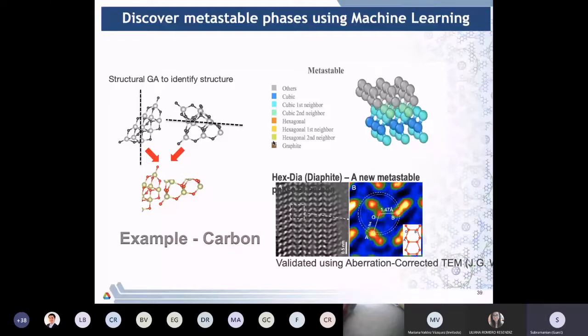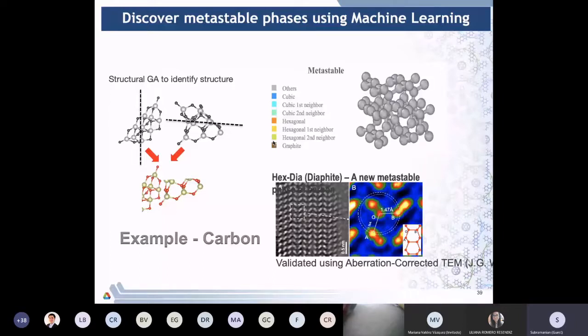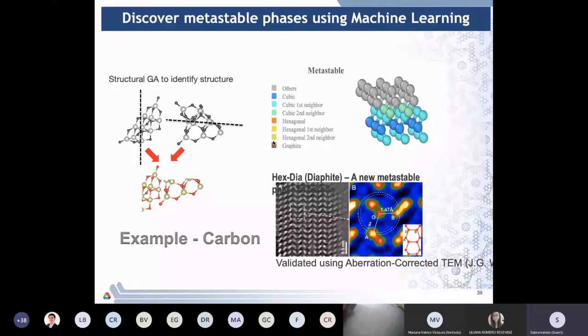So beyond graphite, diamond, and amorphous carbon, there are at least 1,000 different bulk phases of carbon that are available, and they are within 0.5 electron volts per atom away. So meaning that they can all be synthesized and seen in experiments. So the first task is to systematically explore these metastable states. You could either use a genetic algorithm in a structural way to identify these metastable phases, or what we are doing is to use more powerful techniques such as MCTS to operate in the structural space and identify these metastable phases.